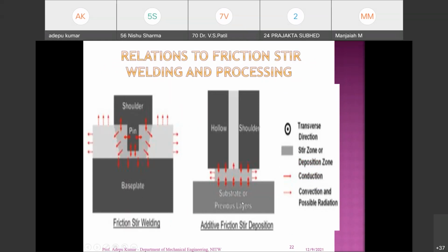So yes, you can see these two pictures, in both friction stir additive manufacturing and additive friction stir deposition. So I want to generate this component. Initially, I have to put all the sheets together. Then the pin is inserted between all the sheets. Then I rotate the shoulder and move it perpendicular to the slide so that the material movement takes place from here to here and fills the backside of the pin, so that I can generate this type of component. Whereas in additive friction deposition, along with the shoulder, you have a filler material which can be deposited on the substrate, so that because of the friction, the material is deposited on the substrate.